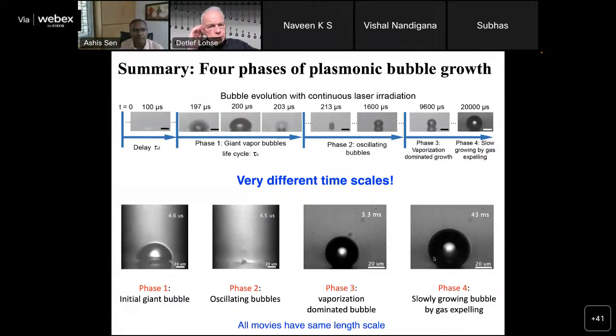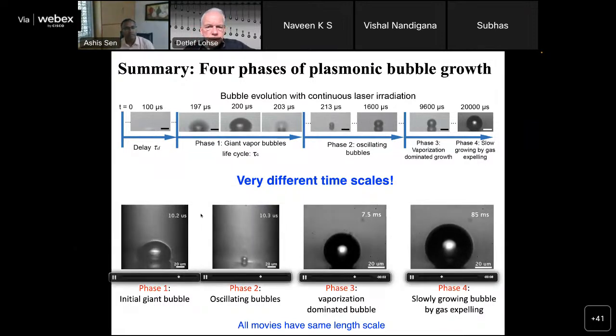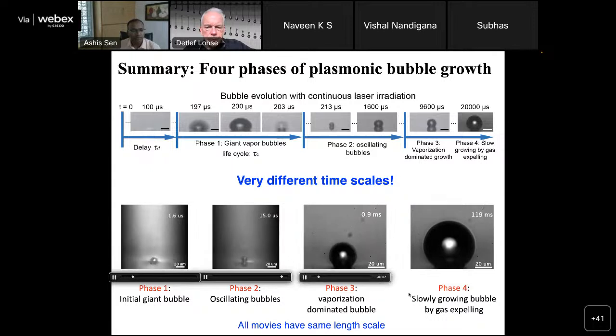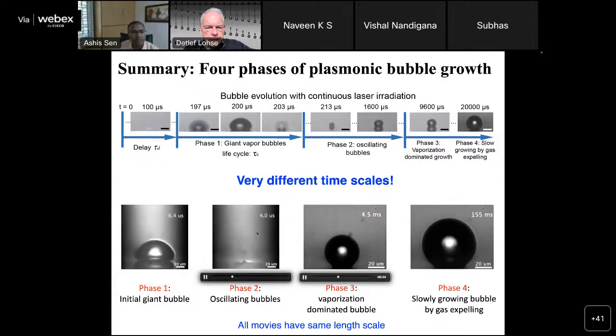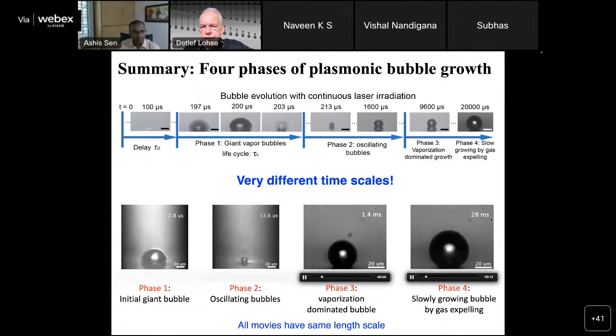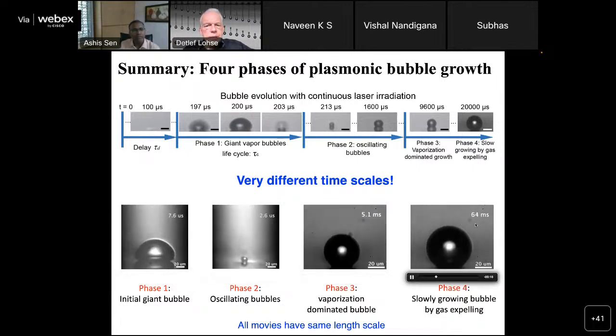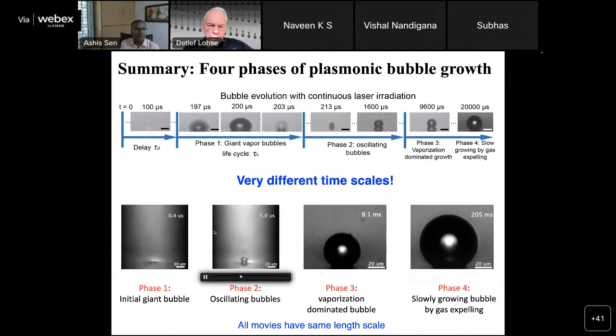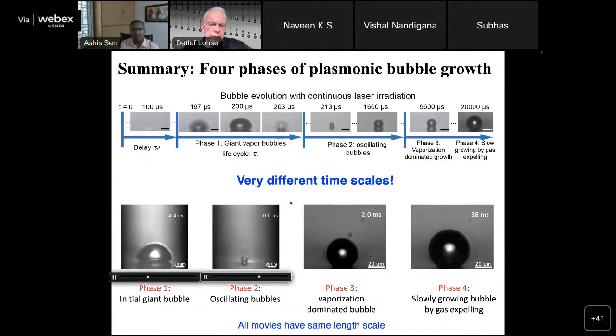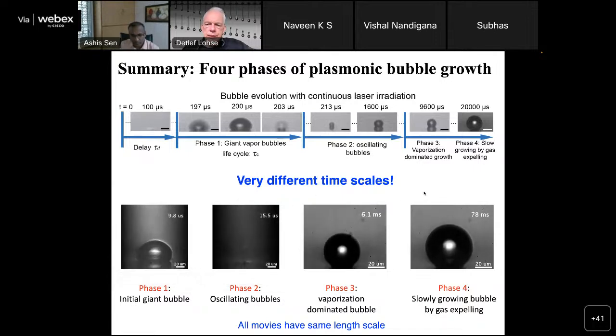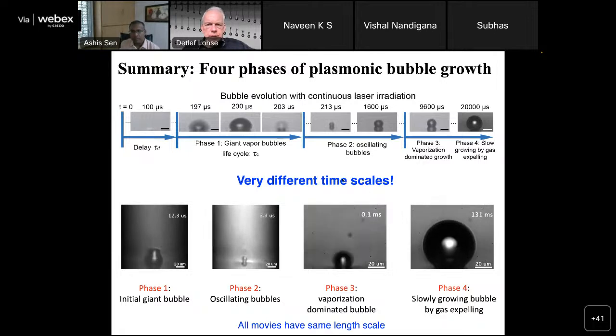So I would like to summarize these four phases here. Watch that all movies have the same length scale here. The time scale is, of course, very different. Here we have microseconds, here we have milliseconds, and here we have up to many seconds. And this creation of bubbles by this plasmonic event is so rich that on all time scales, it has really beautiful physics to offer. And with this, I end.